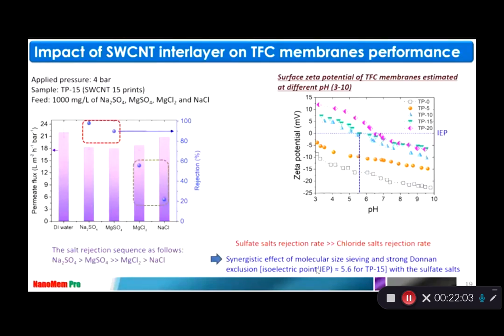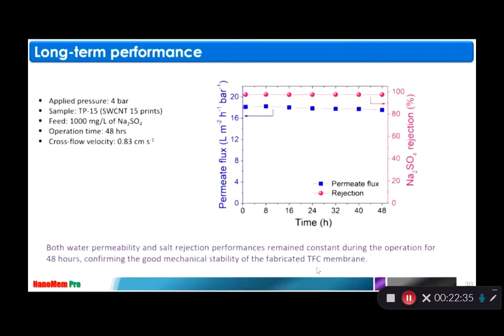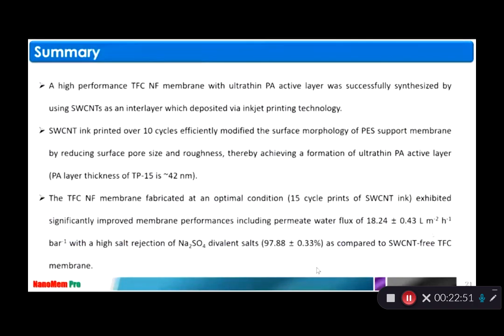Also, we looked at the different salt removal and flux variation. So we found out sodium sulfate has the highest rejection, followed by magnesium sulfate, magnesium chloride, and sodium chloride. And then the zeta potential also gave us good insight into the synergistic effect of molecular size sieving and strong Donnan exclusion effect with the sulfate salt. In the long-term experiment, the water flux and rejection were very stable. So we found out that this printed membrane shows good potential to modify the overall membrane surface characteristics.